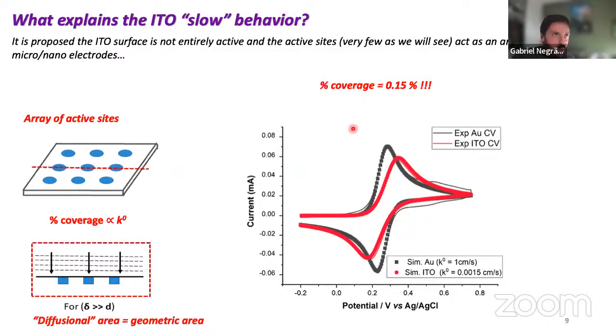And a lot of people, much smarter than I'll ever be, have thought about that back in the day. And they came to a brilliant conclusion. That's the fact that actually ITO, because of the material that we deposit on the surface, we do either chemical vapor deposition, we can use sputtering, it's not 100% active, right? We have islands of activity and areas that are not that active because its deposition is not very uniform. And if you look at an SEM of ITO, that kind of ties nicely because it's a very rough surface.